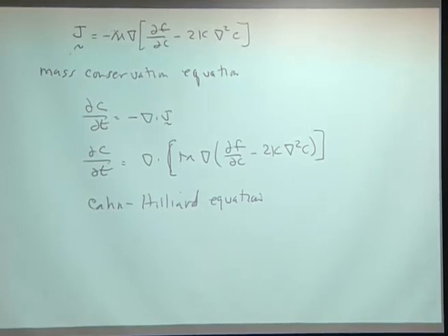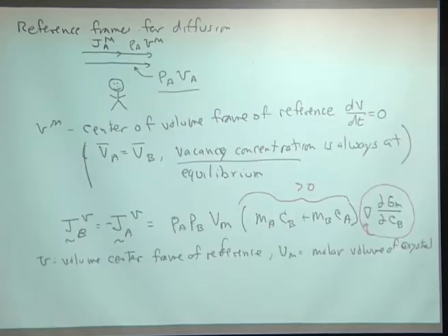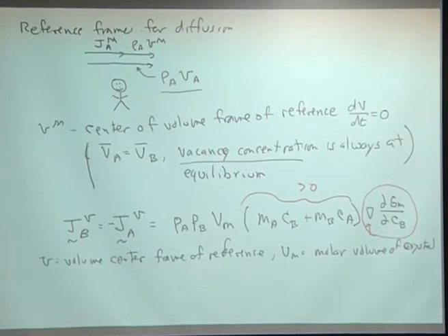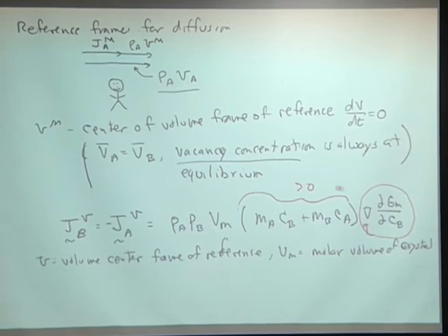So in general, this gradient energy coefficient here that basically tracks the energy associated with gradients in the system, and the mobility here can be functions of composition. And in fact, if you remember the definition of the mobility, this mobility basically involves all of these terms here, this capital M. And you can see that we're going to take all of this stuff to be a constant, independent of composition. And so that's an approximation right off the bat. But nevertheless, that's what we're going to do.